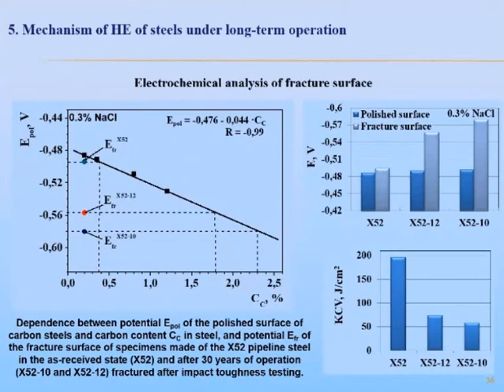And according to the obtained dependence, this difference in potentials was explained by the increase in carbon content due to precipitation of carbides directly on the fracture surface. That is, the fracture surface was enriched by carbon compounds. This fact can serve as proof of the assumption that long-term operation of pipeline steel caused its embrittlement due to precipitation of carbide nanoparticles not only at grain boundaries but also at intragranular defects. And hydrogen absorbed by steel under operation significantly influences this process.